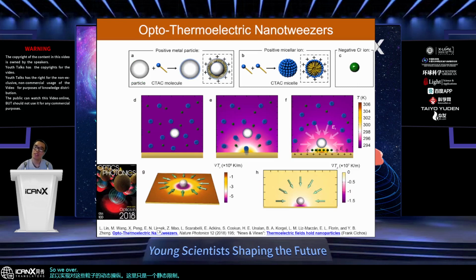So we overcome this limitation by looking into a phenomenon called the optothermoelectric effect. Simply speaking, as figure D shows here, this is a cross-section, and we have a substrate which can absorb light and turn light into heat. And this is a solution. In this solution, we have the particle, the white ball, that we are going to trap using the laser beam. But we added a little bit of additional things in this solution. We added a surfactant, CTAC. This surfactant molecule serves a few roles.